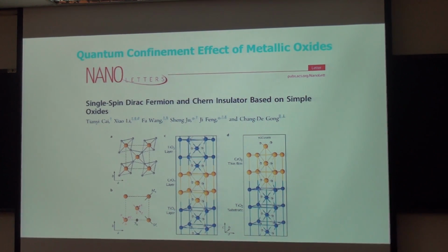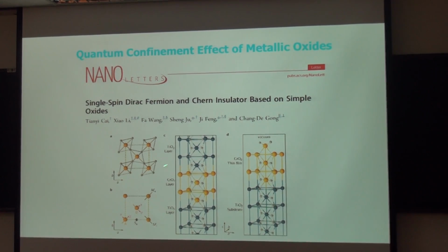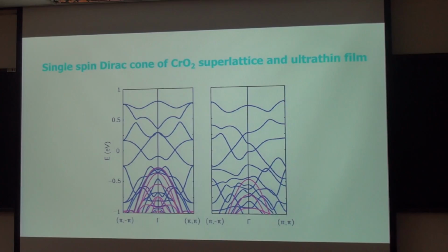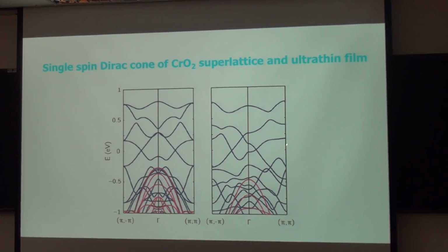But interestingly, at the critical thickness, we have found a very particular kind of band structure. For this material, we have studied two kinds of ultra-thin system. That is a superlattice structure as well as a thin film structure. In both cases, we find the so-called Dirac cone electronic structure at the Fermi level. And interestingly, this Dirac cone is a single spin, that is, fully spin polarized.